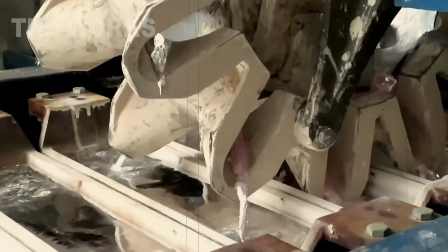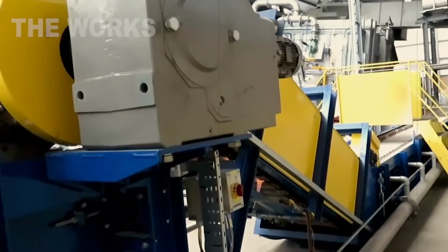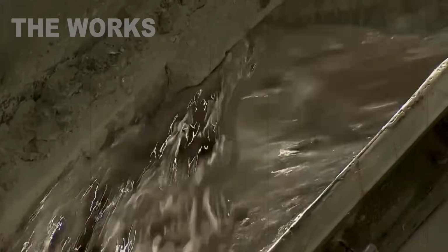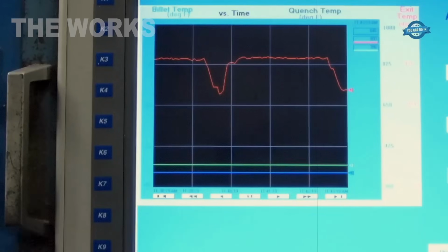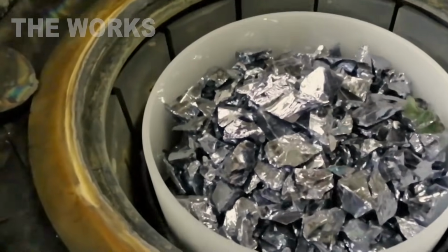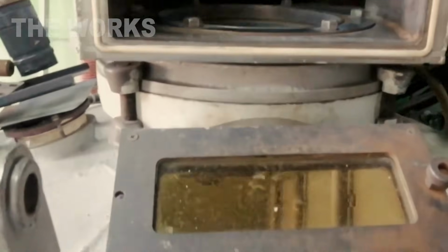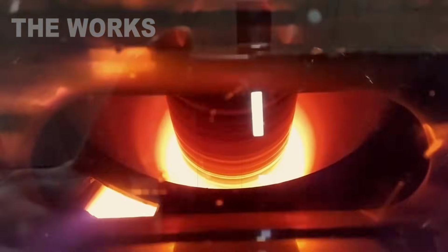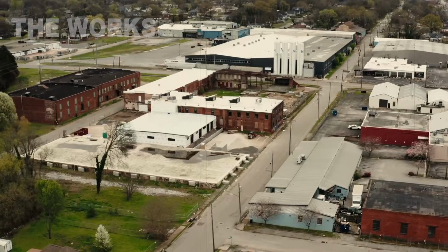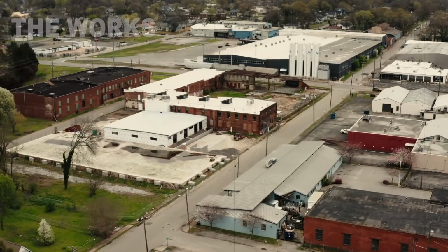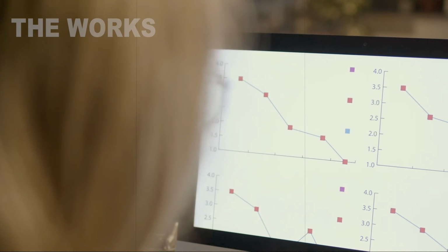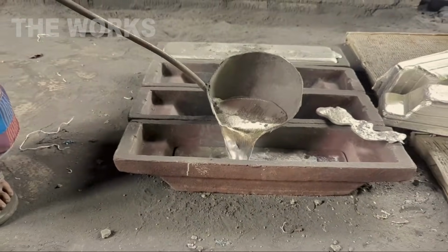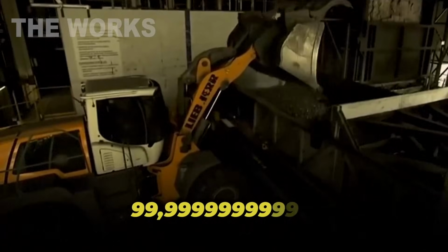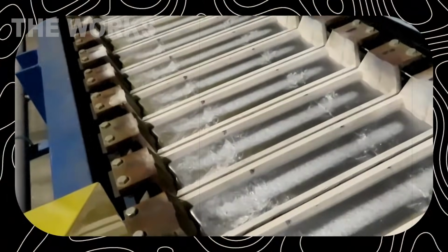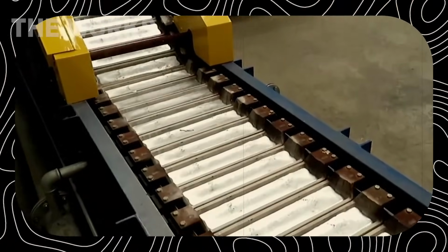This isn't pure silicon yet. This is metallurgical-grade silicon, about 98% pure. It contains impurities: iron, aluminum, calcium. For metallurgy or silicone production, that's good enough. But for electronics, absolutely not. Microchips need silicon that's 99.999999999% pure. That means for every billion silicon atoms, there can be no more than 1 impurity atom. Reaching that level of purity is a task that borders on magic.